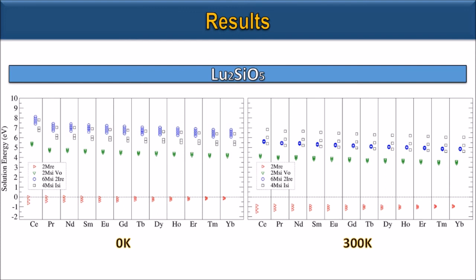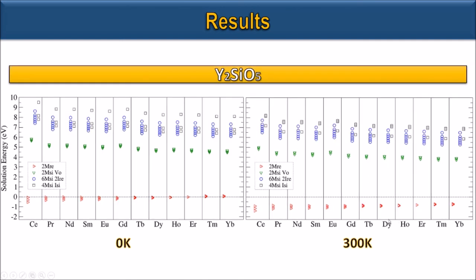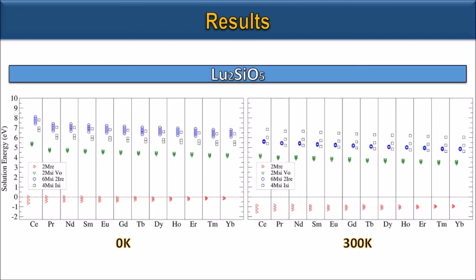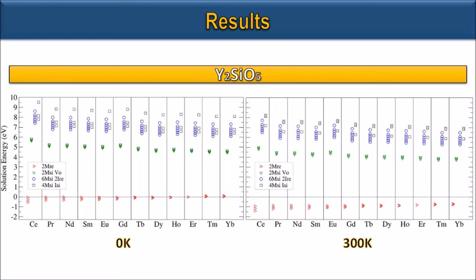We see clearly that the defects with the lowest energy cost are those involving the replacement of 3+ host rare earth ions with 3+ doping rare earth ions, for both lutetium silicate and yttrium silicate, at both temperatures. We also see that doping with the cerium 3+ ion always gives a lower solution energy than the other dopants. This ion produces less distortion in the lattice, which may be linked to its ionic radius compared to the rare earth hosts and other dopants. And like we saw in unbound defects, the solution energy decreases with increasing temperature, for both structures.